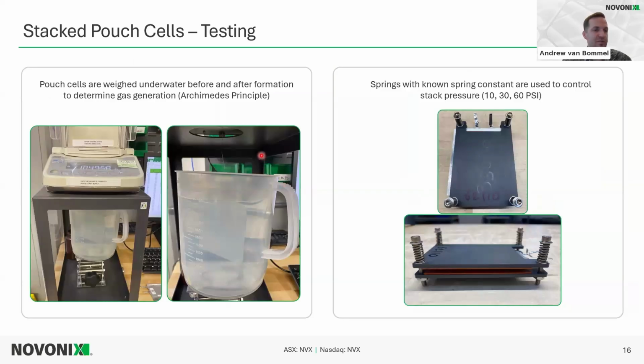In terms of testing the pouch cells, we weigh our pouch cells. So after filling, we weigh those pouch cells underwater before and after formation, and that allows us to determine the volume of gas generated during formation with Archimedes' principle. We can also do this after testing as well to see the amount of gas formed after testing.